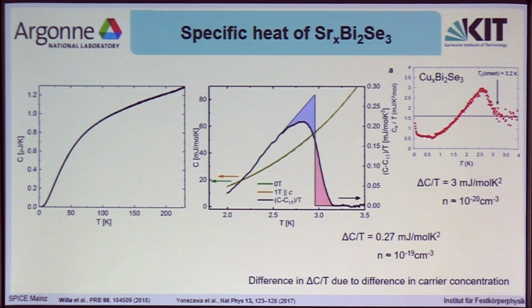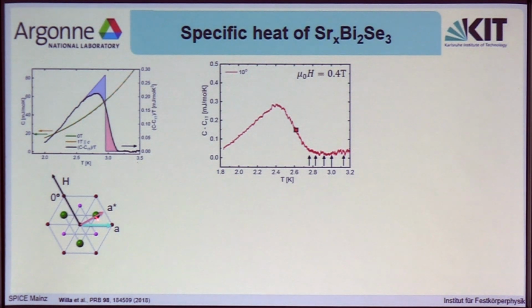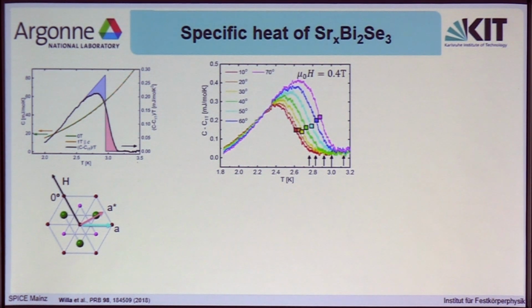in the plane. And in order to do this, we apply a field of 0.4 Tesla in the crystallographic plane. And we measure a temperature sweep through the superconducting transition, which is naturally suppressed by the field. However, when you start rotating the field, you will see that the suppression is much smaller as the angle of the field moves in the plane.